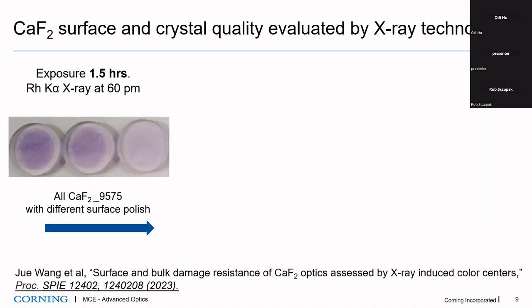And so, speaking of calcium fluoride, it's a fun crystal material to work with. In addition to laser testing, we also try to find other alternative ways. Here is an example. We use X-ray, a high photon energy, with a low-loading X-ray emission. We irradiated the crystal to understand how the color formation is related to the surface quality.